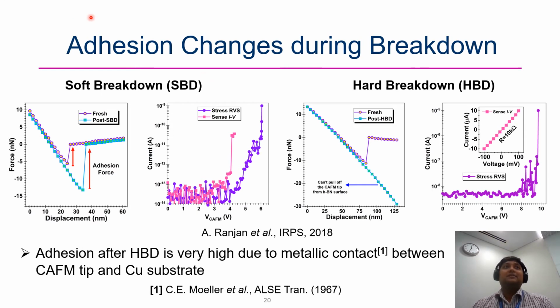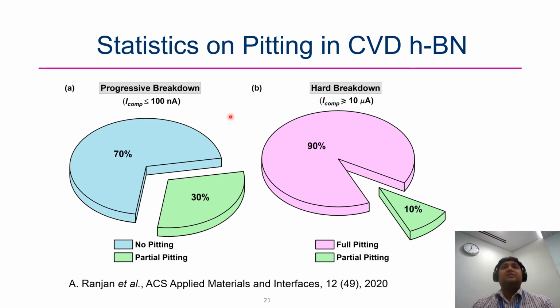So we did carry out some statistical analysis to understand more about the pitting in the CVD hBN. The analysis shows that under soft breakdown conditions, when the current compliance is less than or equal to 100 nanoamps, about 70% of the locations show no pitting, and in only 30% of the locations there is partial pitting. However, the situation is very different in hard breakdown condition. When we keep the current compliance above 10 microamps, about 90% of the locations show full pitting. So the hBN is removed as the breakdown happens, and only 10% of the locations show partial pitting.